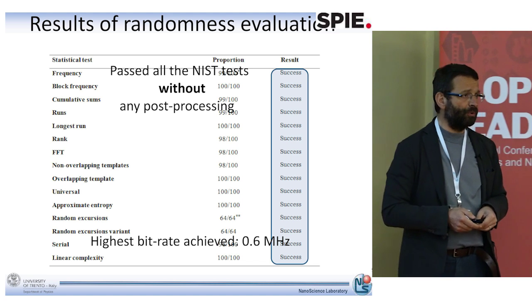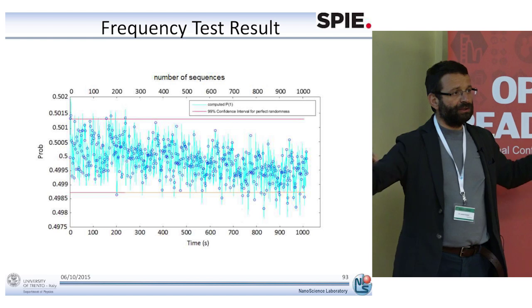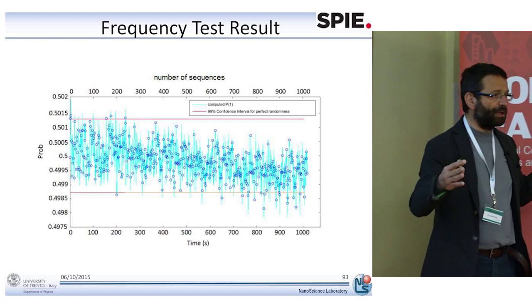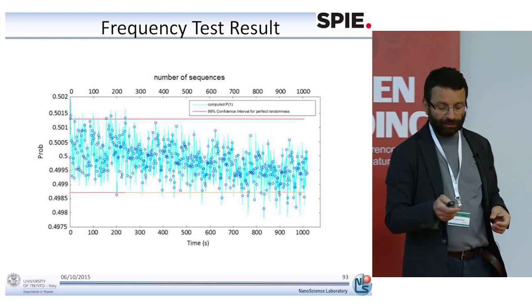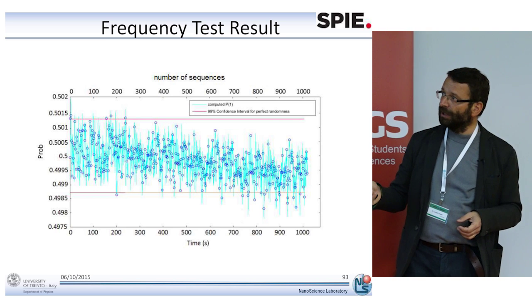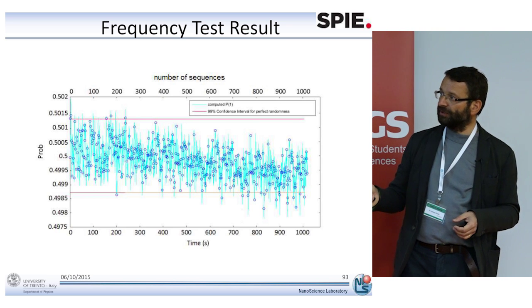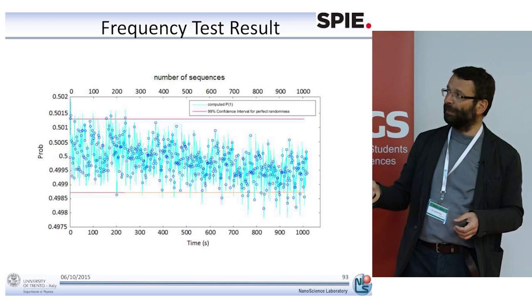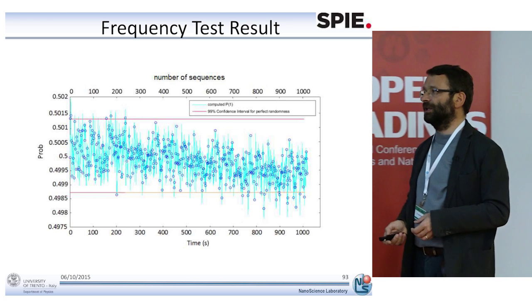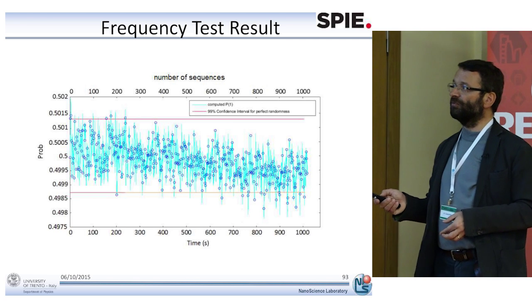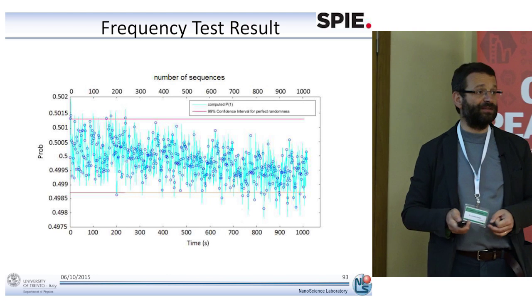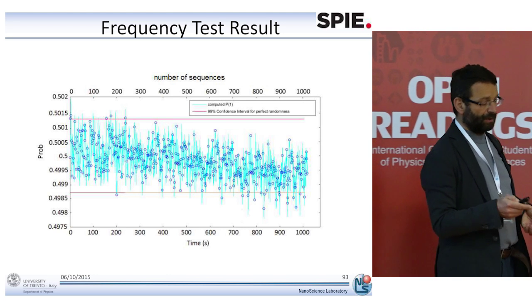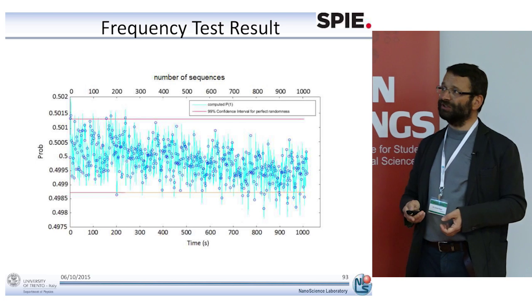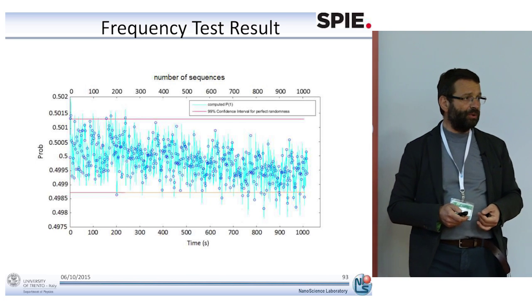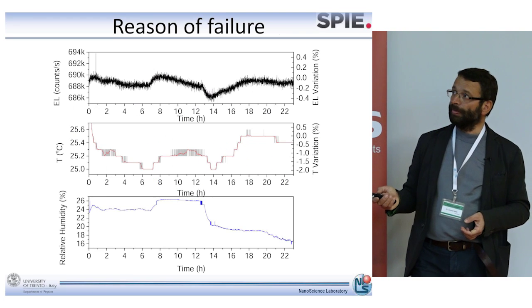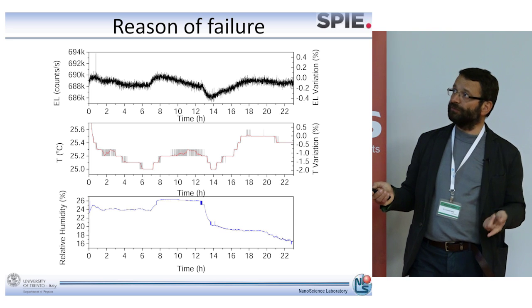Everything was good. But then we enlarge the time frame, we enlarge the observation time. And what we do observe was that after a while, after 500 seconds, the probability starts to get smaller than 0.5. So here the probability to get 0 is larger than the probability to get 1. And this is not good because this is not a good quantum random number generator. And so we look at the reason for the failure.